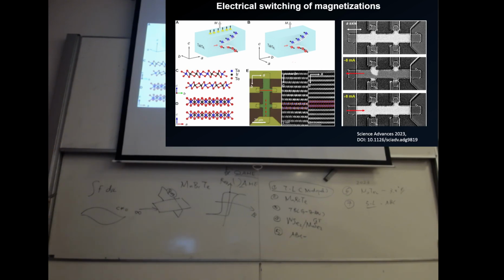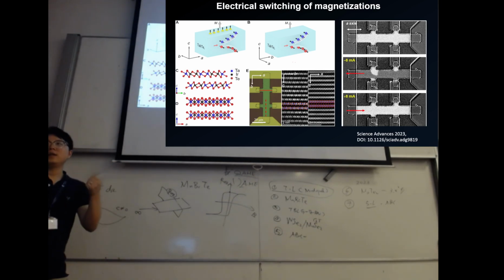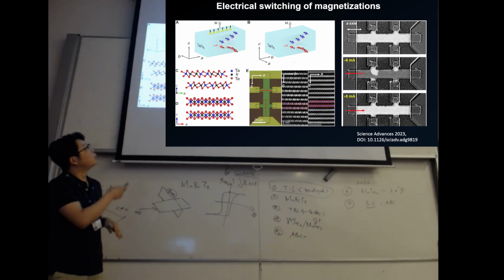And tantalum iridium telluride also gives very high spin-orbit coupling, so that as long as you pass current through the bulk, it will automatically be spin polarized towards the up and down surfaces, so that you have a spin polarized current flowing in the top surface and in the bottom surface with differently aligned spin directions. If you reverse the direction of current, the whole spin polarized current will be reversed too. That means if you place another magnet on top, and as long as this current is strong enough, the spin polarization of the current will influence the spin polarization of the material placed on top. So that means it allows us to tune the magnetic moment flipping by injecting current through the SOC material.